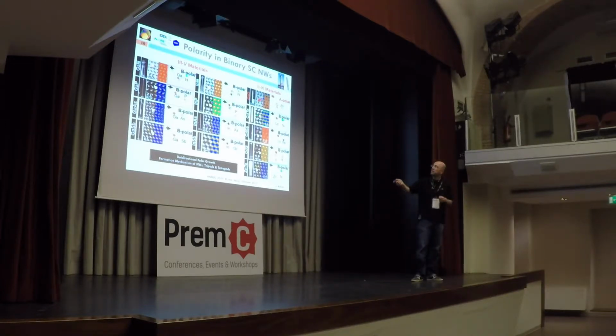That means the anion is always on top. So nitrogen, phosphorus, arsenic, or antimony is always on top and is driving the growth of these materials. If you try to change the polarity under the same growth conditions, these materials do not grow at all. You can tell me that I'm a liar. It's not exactly true, because if you change the growth conditions, then you change the growth rate, the growth is not so fast as in this case, and you can grow in the reverse polarity.